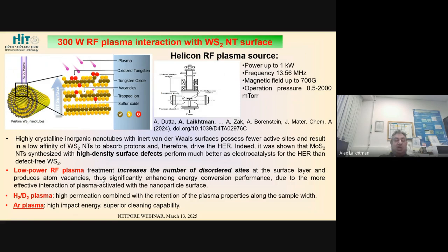So hydrogen plasma, sometimes we use the deuterium plasma for measurements to be sure that the result comes from plasma and not from any other process, because there is high permeation of hydrogen combined with the retention of the plasma properties along the sample width or thickness. So hydrogen plasma and hydrogen excited molecules by plasma go much inside of the layers of the nanoparticles. While argon plasma has no chemical effect, but just high impact energy and superior cleaning capability.